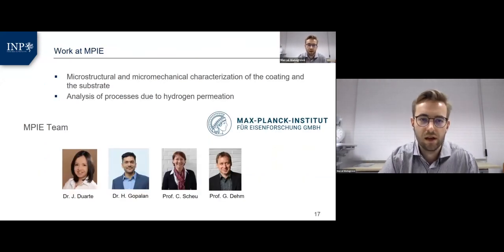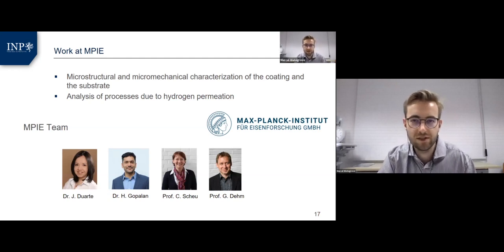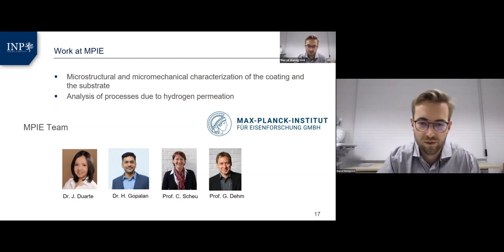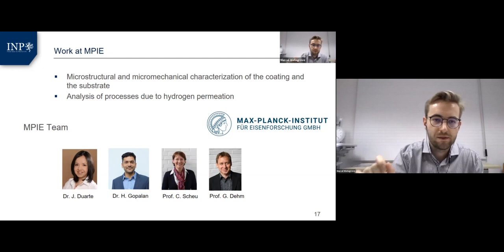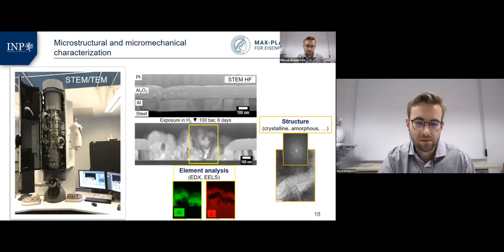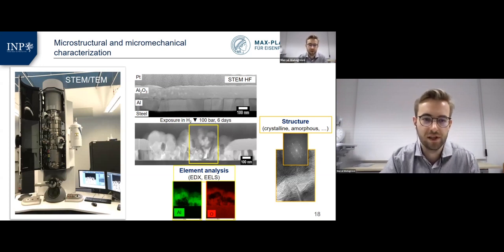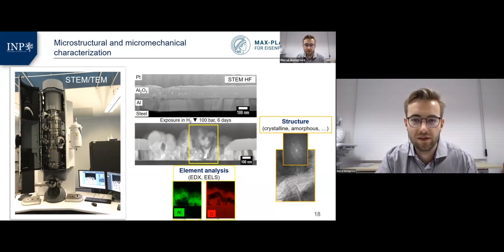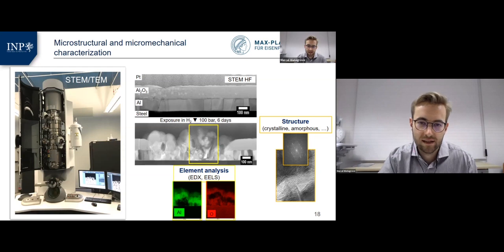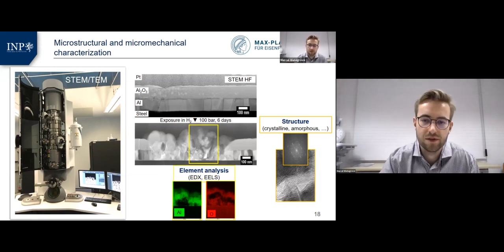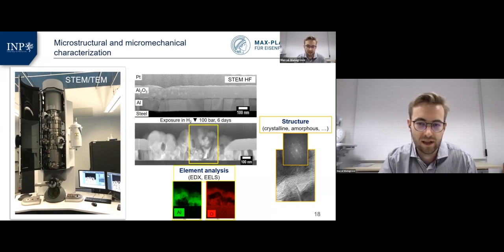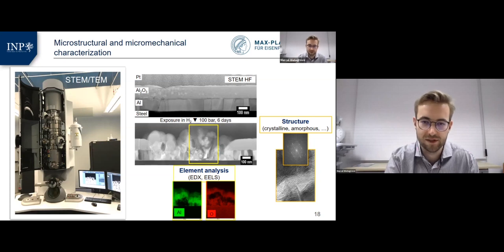Our partners at the MPIE have expertise in the microstructural and micromechanical characterization, both of the coating and the substrate, and the analysis of processes due to hydrogen permeation. These are the work groups of Professor Christina Scheu and Professor Gerhard Dehm. And here, first and foremost, transmission electron microscopic imaging is possible of our thin layers, looking into the morphology and the crystalline composition at a nanoscale of our coatings, both as prepared and also of damages caused by hydrogen. As I mentioned, with respect to crystalline and amorphous materials, but also achieving a localized measurement of element distributions.